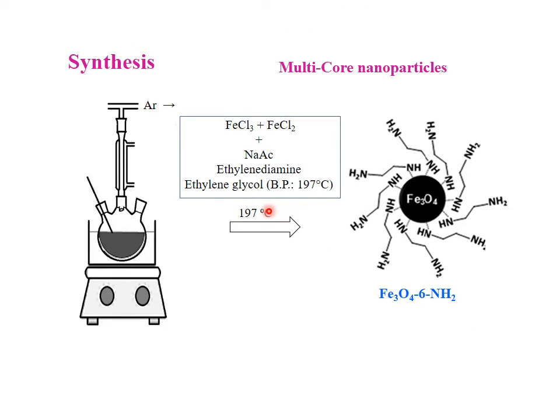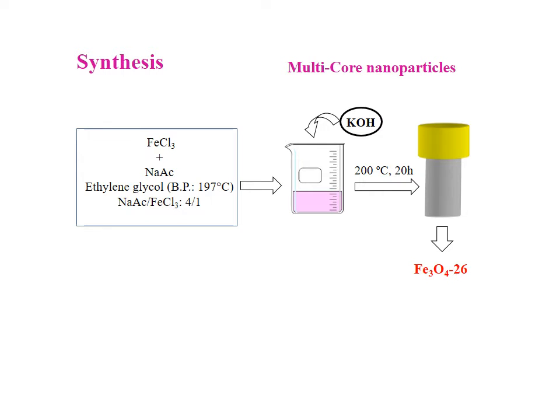Multi-core particles have been prepared by co-precipitation process using sodium acetate as precipitating agent and ethylene glycol as solvent. For the synthesis of the amine functionalized magnetite sample, ethylene diamine was used. In the case of the magnetite 26 sample, the synthesis was carried out under hydrothermal conditions at 200 degrees centigrade for 20 hours.